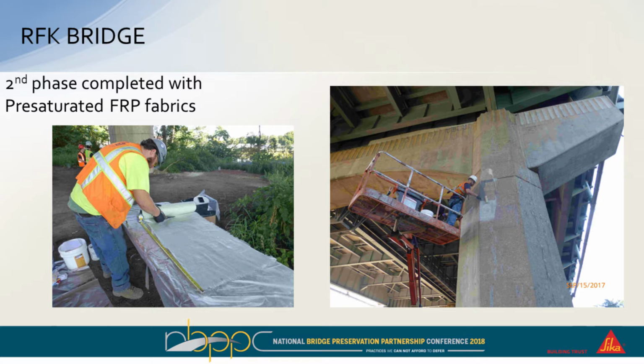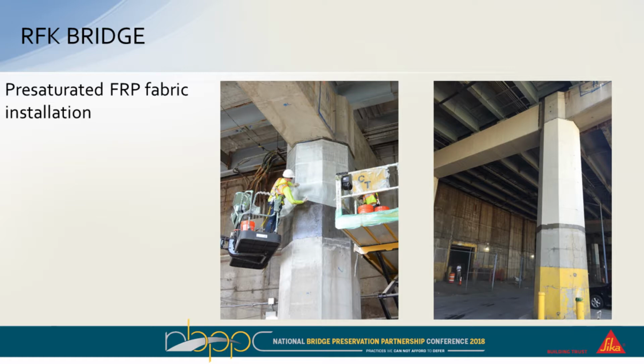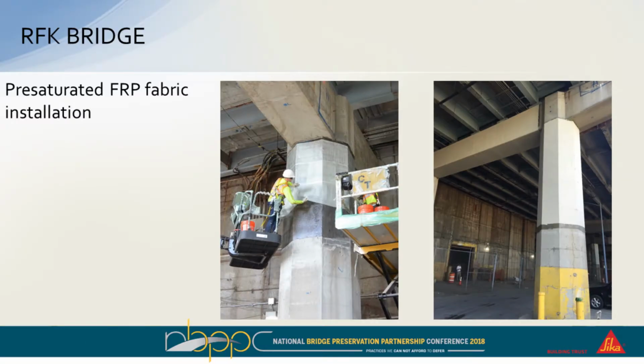And again, here you can see essentially just them opening up the fabric, cutting it to length. After priming the concrete, you lay it right up onto the concrete. So here you see them working off a couple of scissor lifts. In this case, the work crew is really only 2 people because you don't need anyone mixing and saturating. So essentially you just need the guy cutting it to size and bringing it up onto the lift and wrapping it around the, in this case, the column. And the right picture is where they actually, after they put the protective coating on for UV protection.